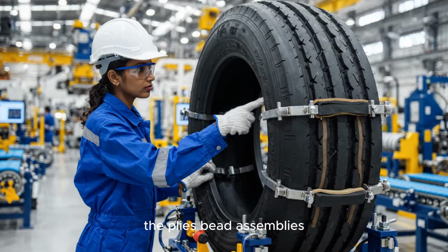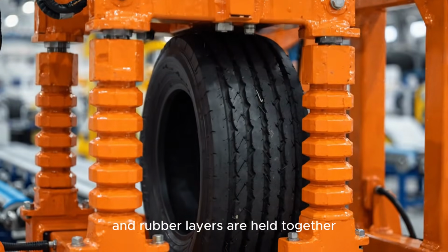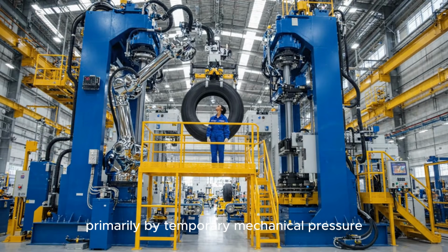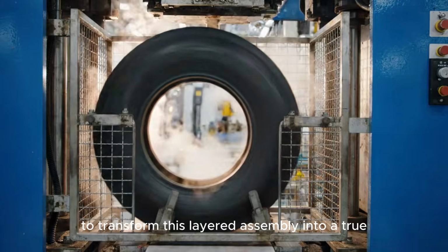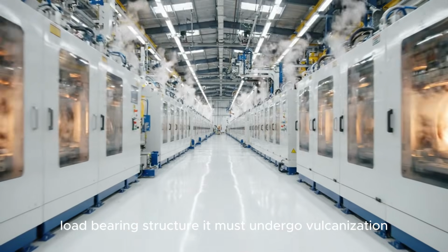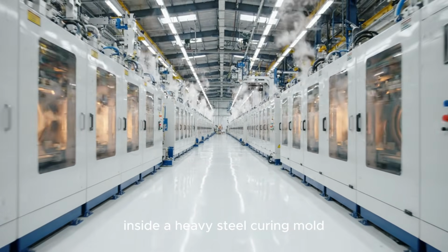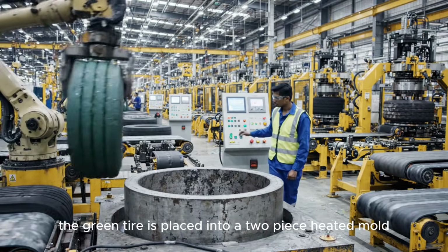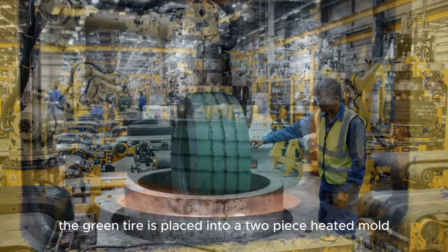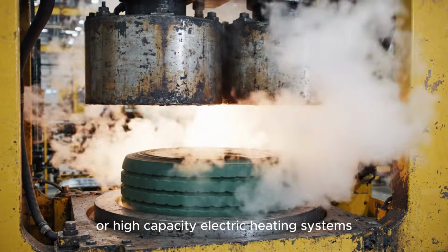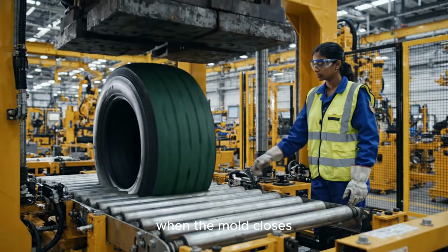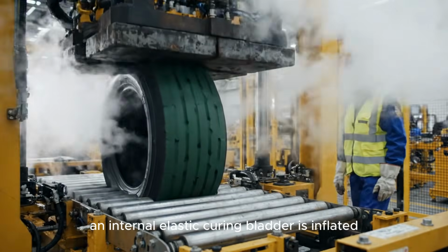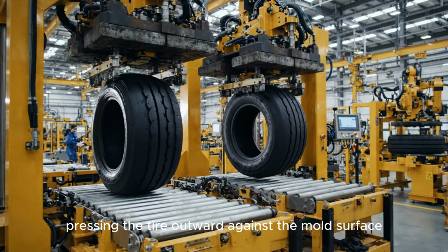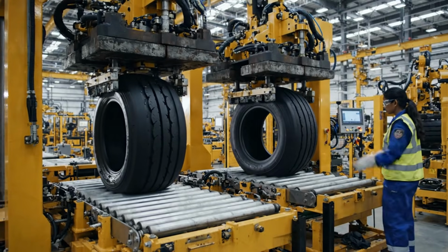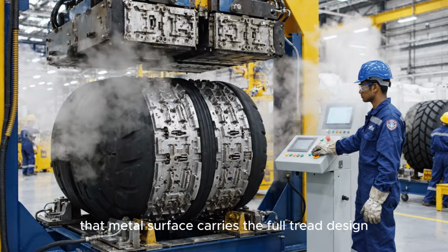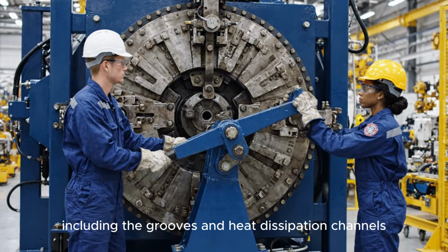The plies, bead assemblies, and rubber layers are held together primarily by temporary mechanical pressure. To transform this layered assembly into a true load-bearing structure, it must undergo vulcanization inside a heavy steel curing mold. The green tire is placed into a two-piece heated mold powered by steam or high-capacity electric heating systems. When the mold closes, an internal elastic curing bladder is inflated, pressing the tire outward against the mold surface. That metal surface carries the full tread design, including the grooves and heat dissipation channels.